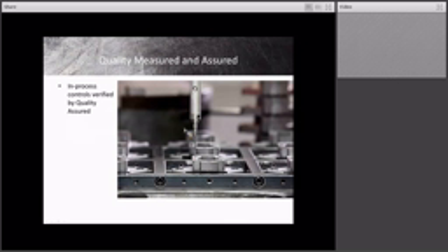Quality, we measure it and we guarantee it to the best of our ability. We verify what we do using CNC-controlled CMMs as necessary. We also have in-process gauging, and we certainly value the use of attribute gauging to ensure fit function capability for the customer. Very often, tolerancing is laid out. What we've found is tolerancing may be laid out by engineers for one practice, but by the time the part gets to finished, that may not be the case. The part may not fit, and attribute gauging can often benefit in use there.